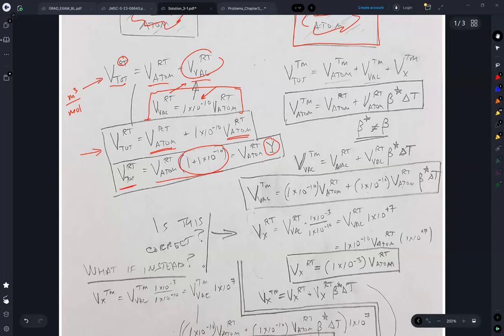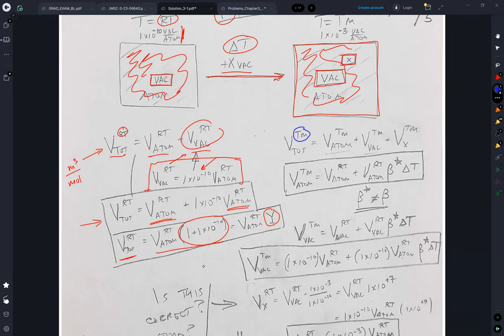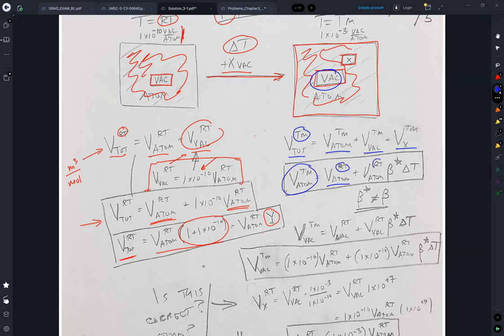Next, if you look at near the melting temperature — which is given in the problem — the total volume is the volume of the atoms at melting temperature, the volume of that vacancy cluster, and the volume of the extra vacancies. So I can write the volume of the atoms as the volume of the atoms at room temperature plus the volume of the atoms at room temperature times beta star delta T.